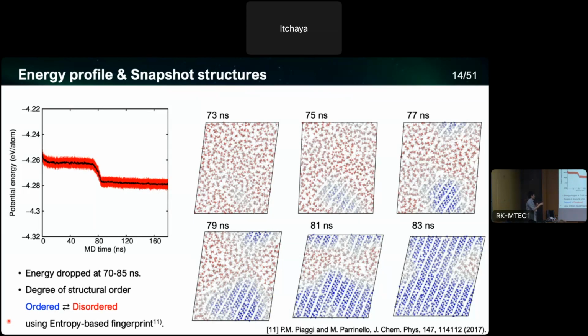Which is indicating that some phase transition occurred at this time scale. And then these are the snapshots at 73 nanoseconds to 83 nanoseconds. In these snapshots, we put colors on atoms based on the degree of structural order. So the blue part is ordered, so the surrounding PS4 units are arranged in the same manner. And that part is disordered, meaning which are close to the glass structures. So as you can see, it actually started around 73 nanoseconds.